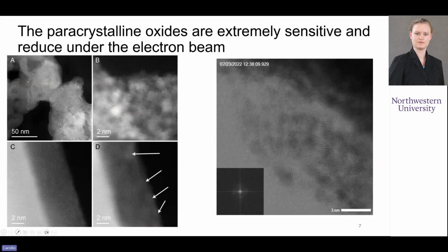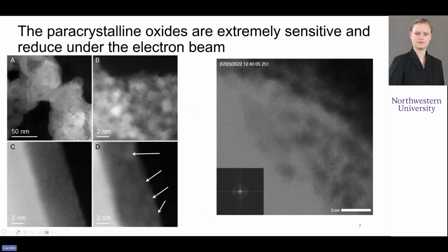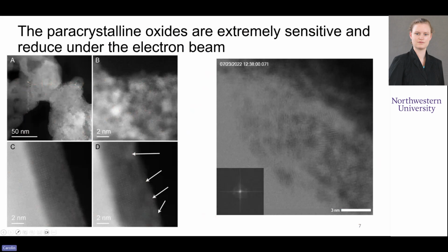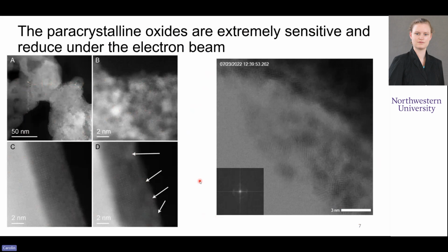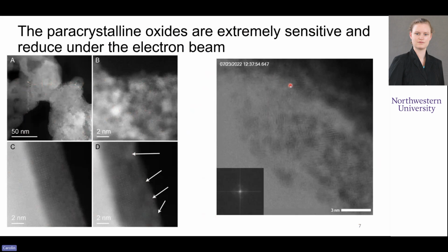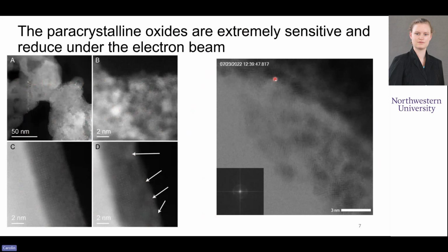So if you look to the right, you can see how under exposure, this material immediately starts shrinking and crystallizing out, and you can see in the Fourier transform how the crystal lattice forms. And I'll let this play for a bit, but you can see how quickly the initial transformation happens. Immediately on the first frame, you see how this starts to shrink, and then the crystallites form. This entire amorphous part becomes less and less and grows over on the surface over here. And if you watch up here, you see the large crystal aggregates that start to form over here.